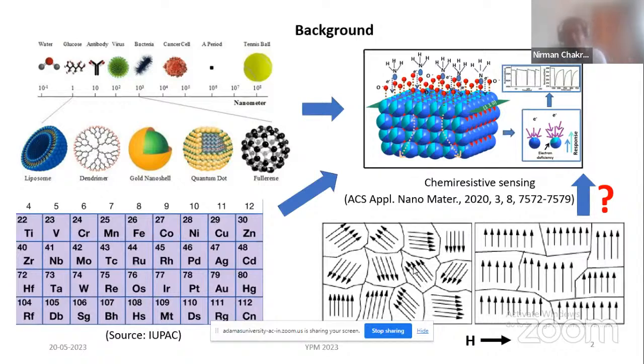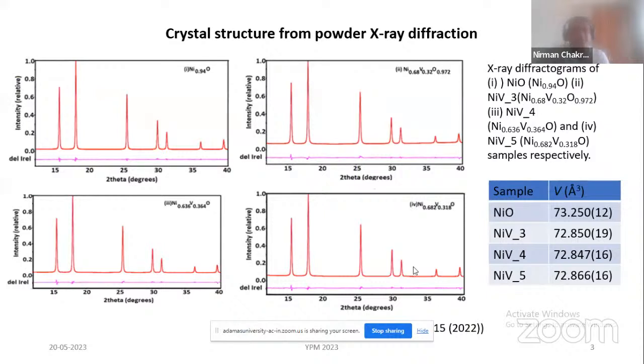So we chose a very standard system, nickel oxide, which is a p-type antiferromagnetic wide band gap semiconductor transition metal oxide. We doped it with vanadium because pure metal oxides have very poor selectivity towards a certain gas as a sensor, and vanadium has multiple oxidation states in the doped form. So we wanted as much electronic structure modulation as possible because of this doping.